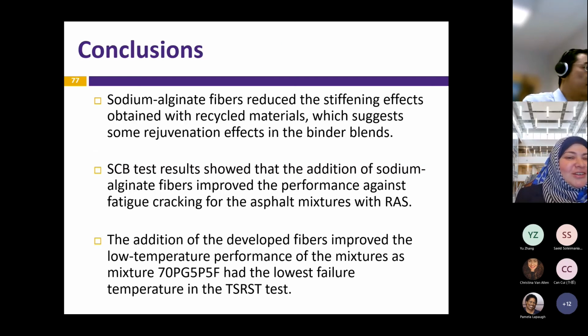So in conclusion, sodium alginate fibers reduced the stiffening effect obtained with recycled materials, which suggested some rejuvenating effects taking place. The SCB test results showed that the addition of sodium alginate improved the performance against fatigue cracking. And the addition of the developed fibers improved the low temperature performance of the mixes, which suggests that it has better performance in terms of low temperature cracking.